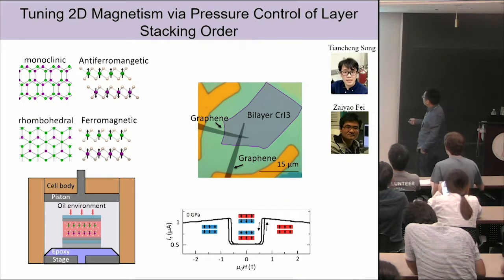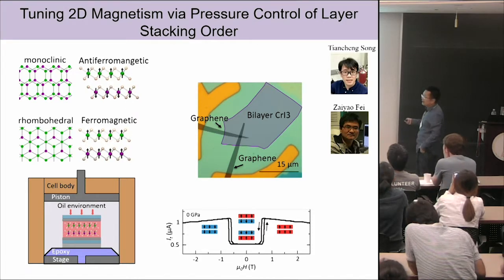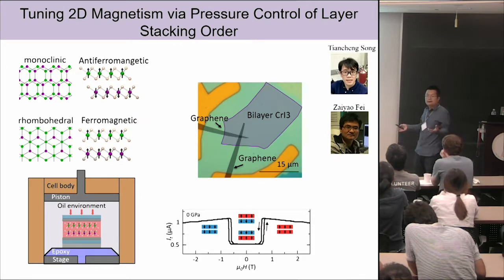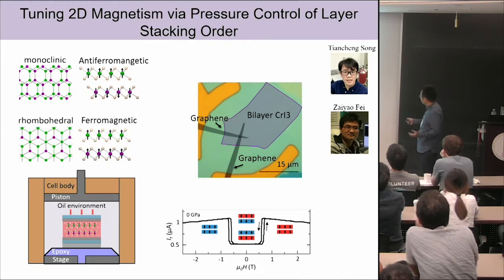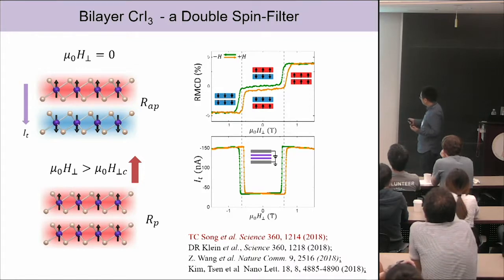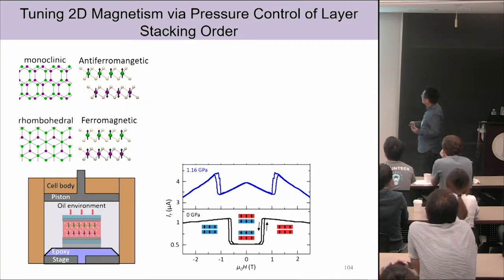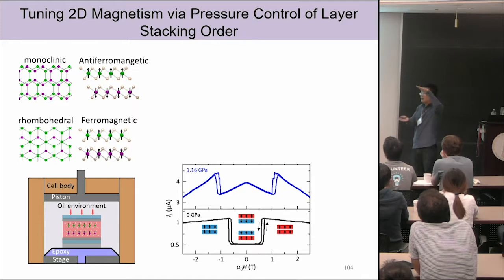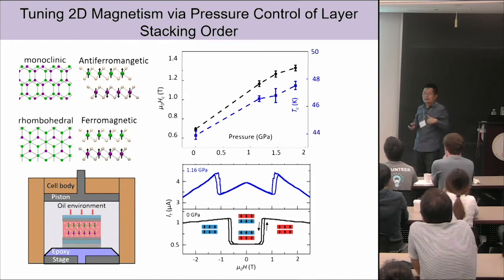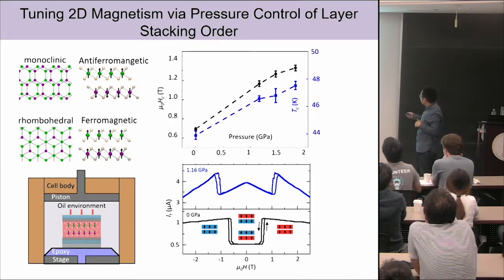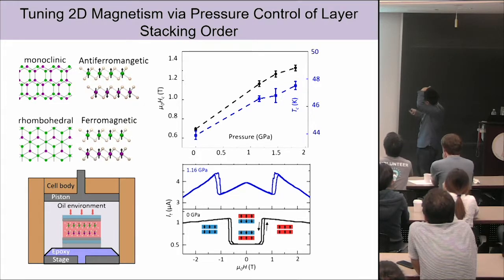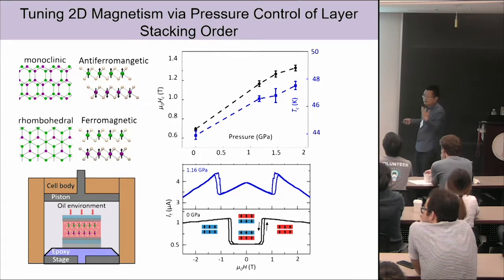We make these samples with basically the tunneling structures I just talked to you about. And we measure the tunneling current at zero pressure. Then we can increase the pressure. Just skip these slides. As you increase the pressure, you can see the critical field for the spin flip transition increases, right? This just shows that by applying pressure, you indeed increase the interlayer couplings, okay? And I can map out the interlayer coupling as a function of pressure, represented by these black dots. We can increase the interlayer coupling actually by a factor of 2.